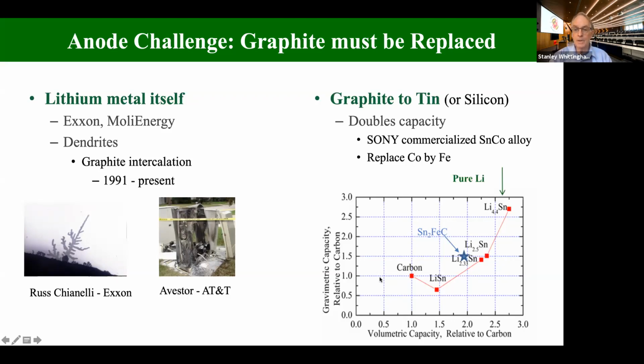So if you look at the plot at the bottom here, everything is relative to carbon. So here's the volumetric capacity relative to carbon. So you can see if you put 2 lithiums into tin, we can more than double the volumetric capacity. And you don't need to go all the way up to 4 to get the advantage. You don't need to stress the lattice that much. If you go as far as 4, you more than double the gravimetric as well. And you can see these materials have essentially the same volumetric capacity as pure lithium metal.